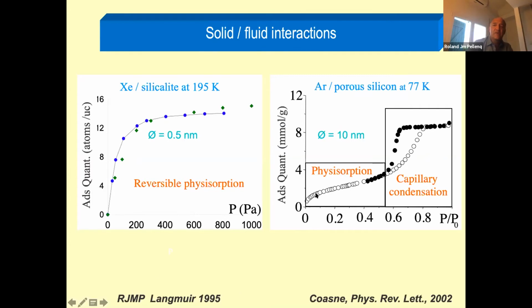Now porous carbon—this plot is from the PhD work of Benoit Coasne. This is argon in porous silicon at 77K. You see, as I said, the physisorption and the capillary condensation, which is obviously absent when you're in very small pores, as I said earlier. Those porous silicons have a very nice, well-defined pore size of 10 nanometers.